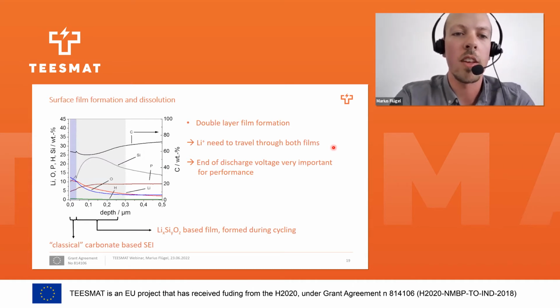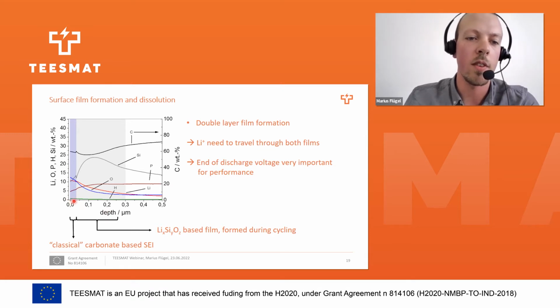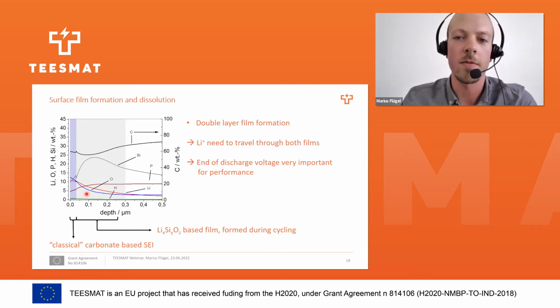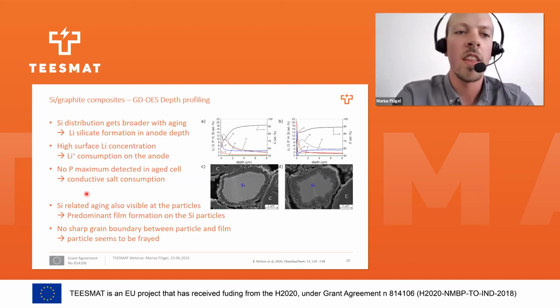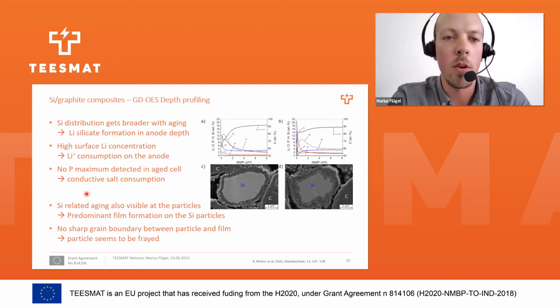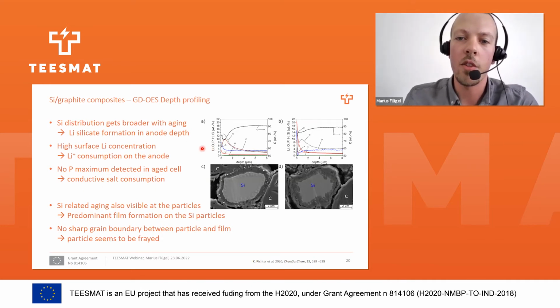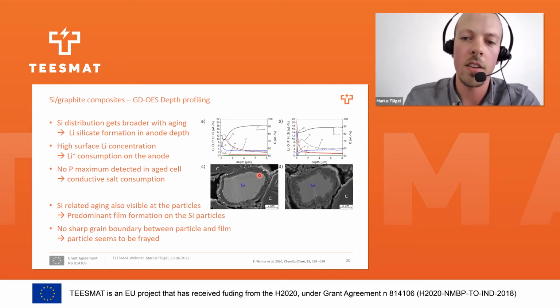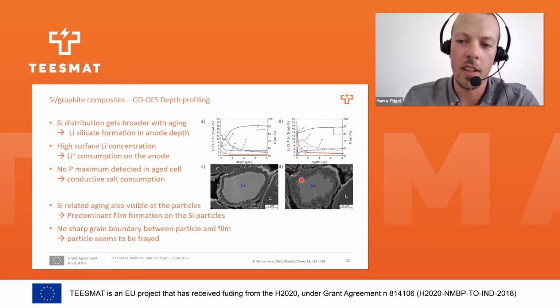We observed a double layer film formation. So there is a classical carbonate-based SEI, which is present in graphite anodes, but also a lithium silicate-based film, which forms during cycling. The silicon film at the surface gets broader with prolonged cycling, and this can also be seen in the cross-section. Here around the silicon particles, we see the SEI film, or the film around the silicon particles, but there is a sharp border between the silicon particle and its film. After cycling for 700 cycles, the boundary between those particles and the film will get more and more diffuse.